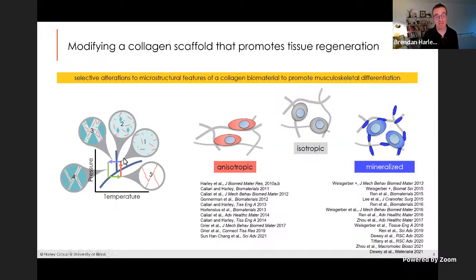And then we freeze it. And as you freeze it, you form ice crystals in the aqueous phase. And so by controlling how fast you freeze or how cold you freeze the material, you can control the size and the shape of the ice crystals that form. After it's frozen, we then sublimate this material. So that means we drop the pressure and increase the temperature, and you can go directly from solid to vapor. So we pull out all the ice crystals as vapor, and what we're left behind is a porous network whose pores are defined by the size and the shape of the ice crystals we form.